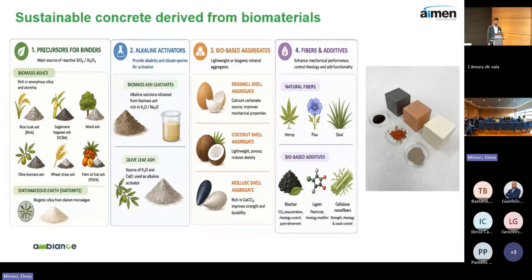Lignin works as a rheological modifier to improve the dispersion and the rheological properties, which is very important for 3D printing. And finally, the last option would be to introduce cellulose nanofibers, which increase the mechanical strength, reduce cracking, and improve the durability of the material.